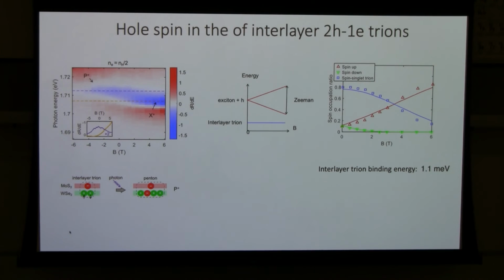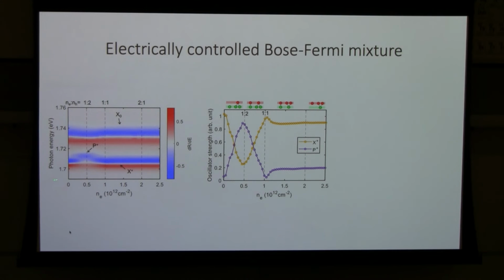So it's about 10 times smaller than the exciton binding energy. With this understanding, we now know that the P plus peak really tells us the trion density, and the X plus peak tells us the free hole density. So if we look at this spectrum while we change the electron density, we can read out the trion density and the free hole density, and see how they evolve when we change the electron density for a fixed hole density.